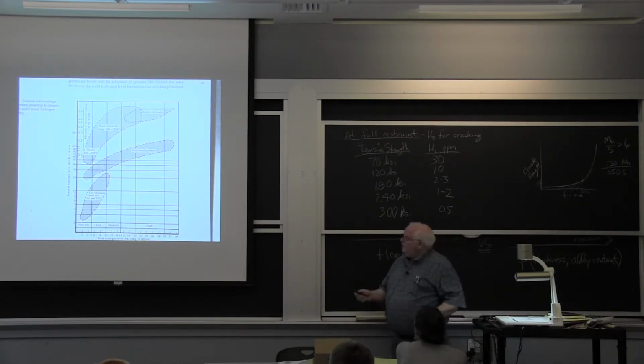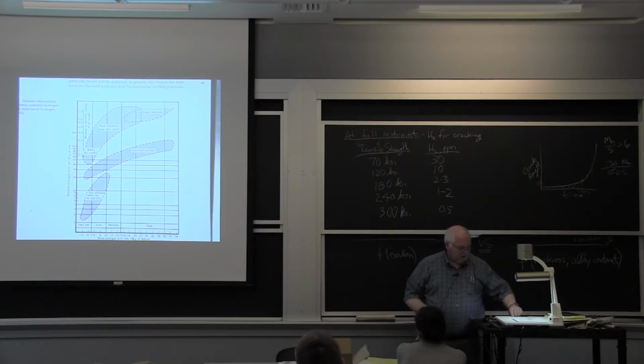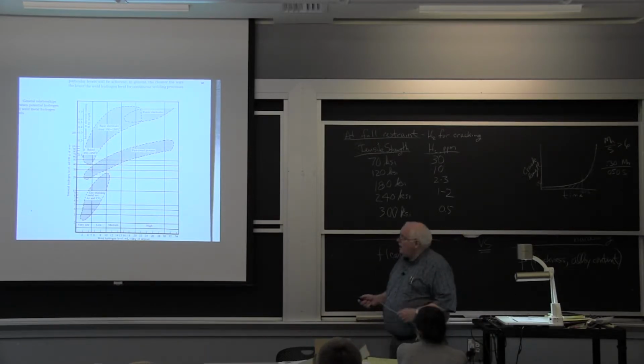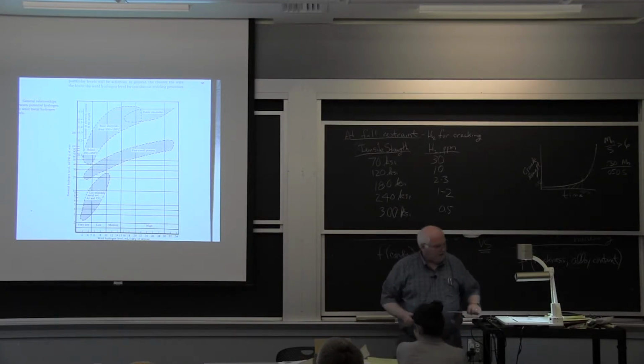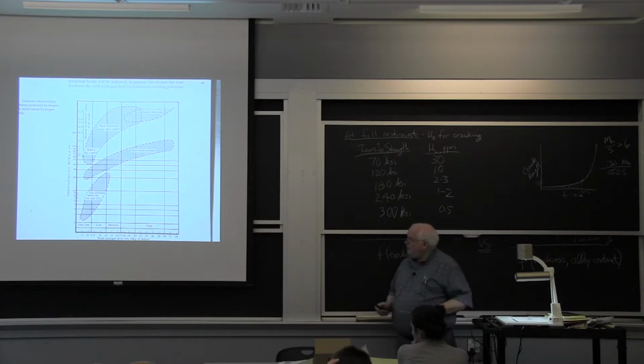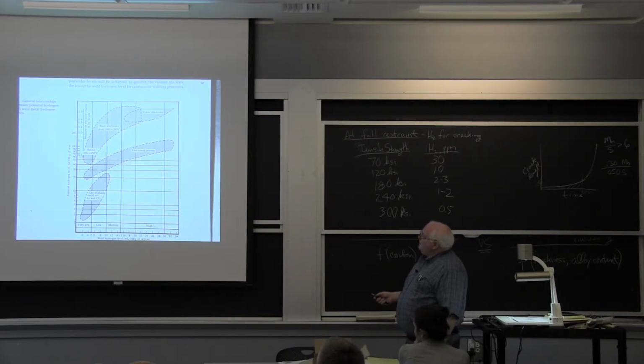I don't have any 70-14s here. You can have very high hydrogen. If you use a basic electrode that's been dried at 100 to 150 C, like this 70-18 that I have, which is not dried, you can have a wide range of moisture in your electrode coating in the flux. Over here they have the weld moisture in, what's it say? Moisture in electrode coating, percent by weight. Well, that's the moisture in the flux coating. Typically, really good electrodes are 0.4. Very, very extra dry electrodes are 0.2. And so you could easily get 5 or 6 parts per million hydrogen in typical mild steel welding.